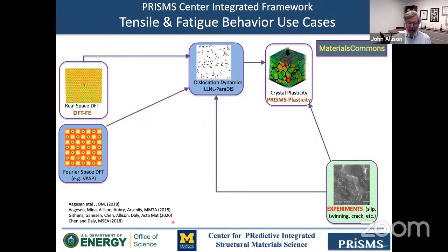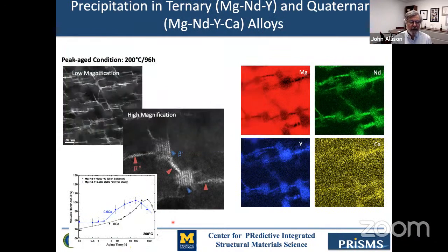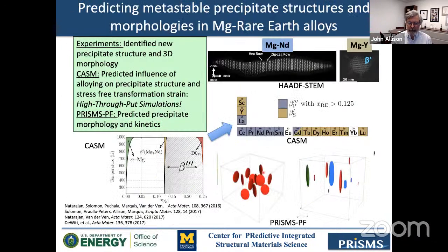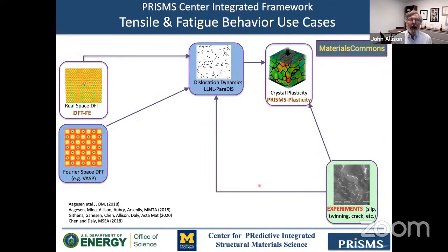And then we are able to map these phase field results shown here, these maps of phase field, to ParaDiS to do dislocation dynamics studies on precipitate spacing. And so then we've linked that with crystal plasticity to predict precipitate effects on strength. And I won't have time to go through that, but there's a number of publications here that are available if you are interested in that area.